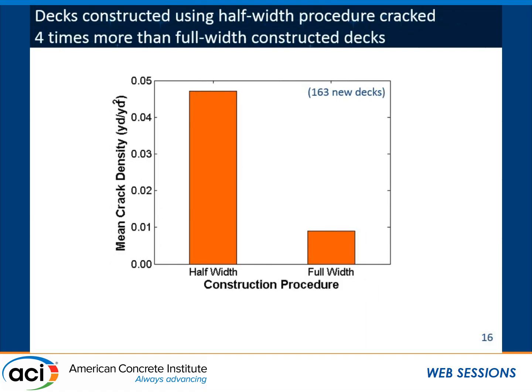We also looked at two methods of construction. One of them is called half-width construction, which means that you are repairing, let's say, half of the deck longitudinally and directing the traffic on the other half. And the full-width construction is that essentially you have a detour and move all the traffic off the deck, and do the repair or the reconstruction. It looked like the half-width construction resulted in a lot more cracking.